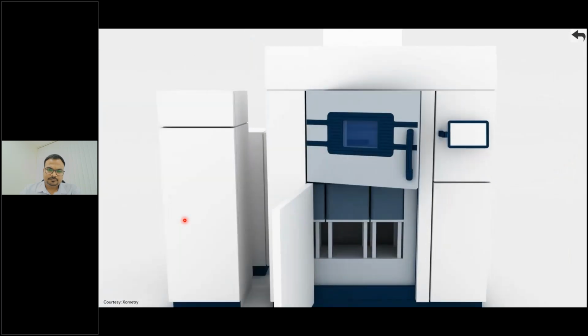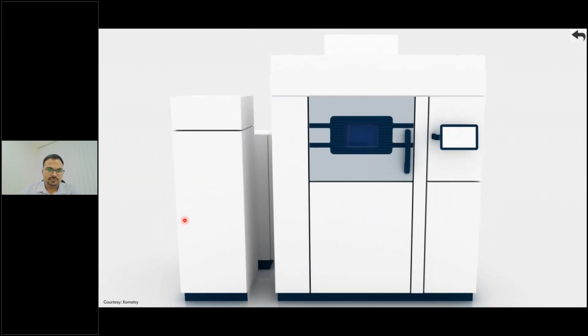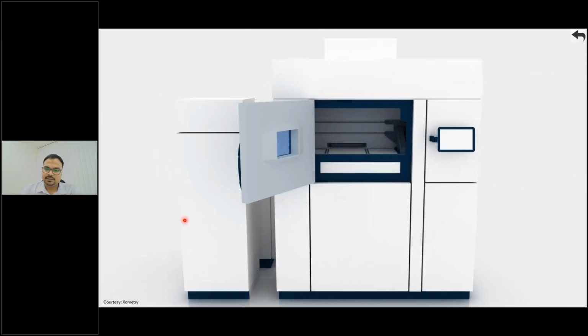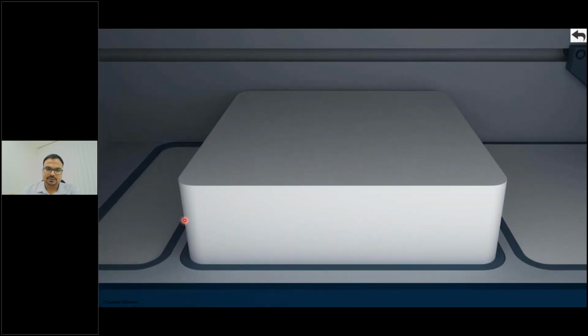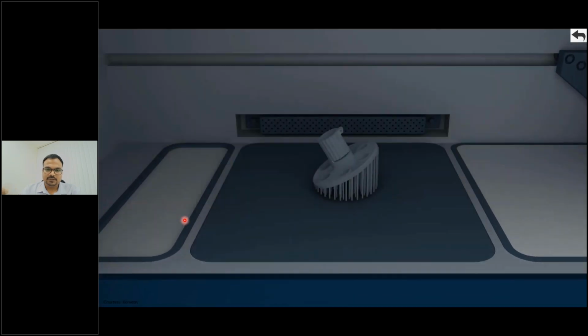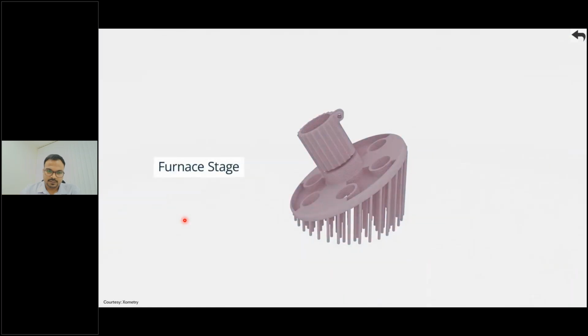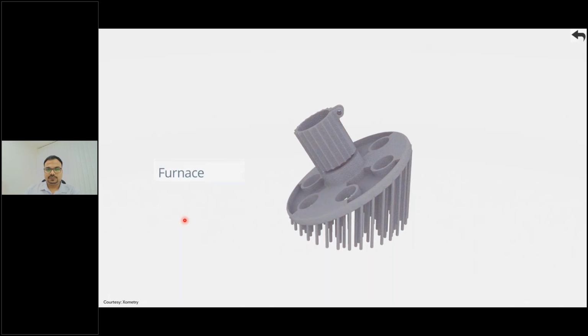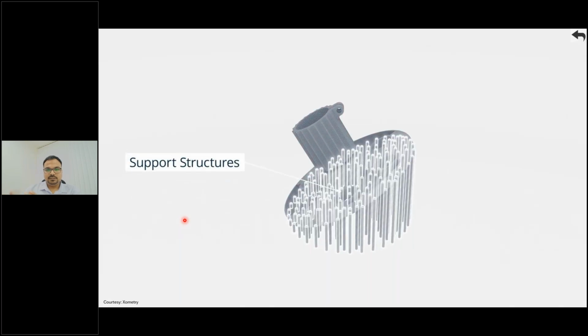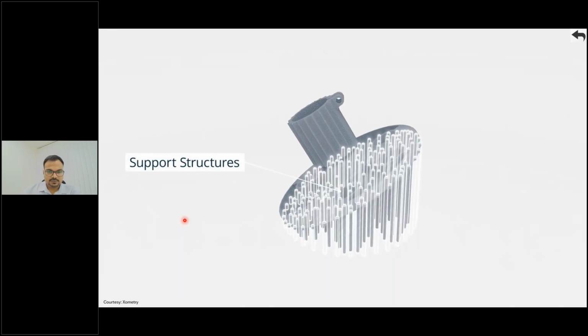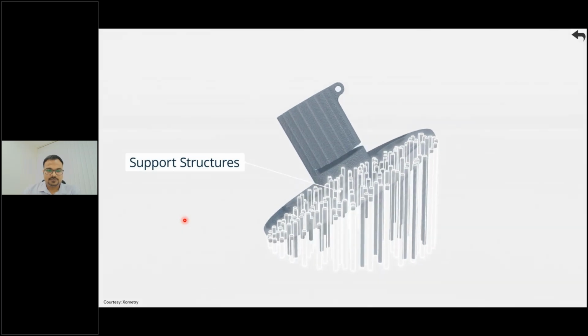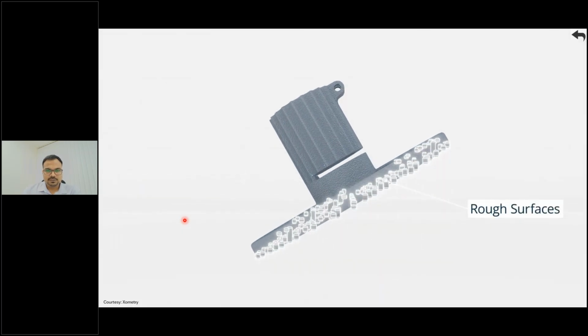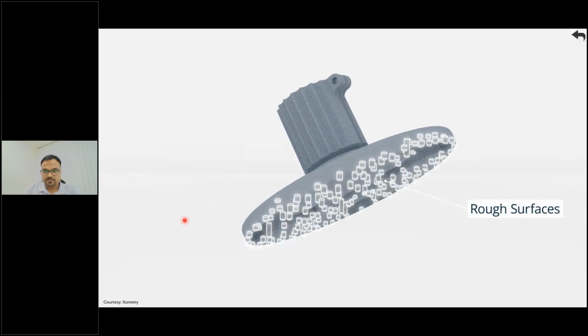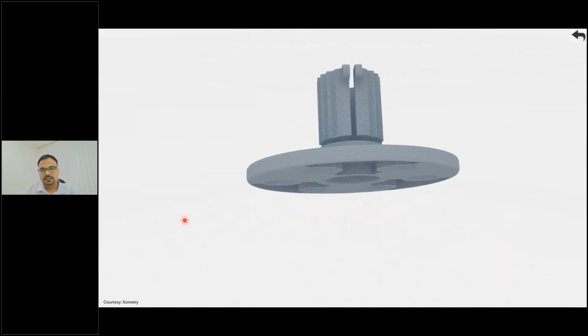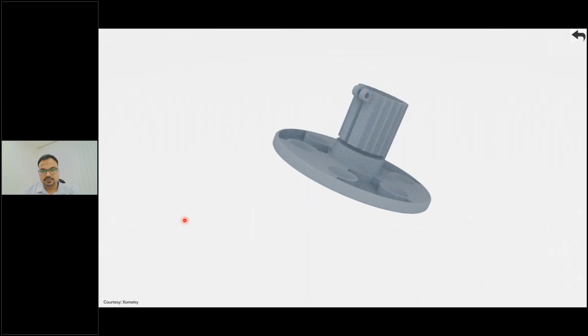And it addresses very minute details. The laser diameter is just 18 microns, so it is able to print starting from 100 micron of the feature as well during the process. Immediately after the printing is done, we take out the model and put it in the furnace for relieving the stresses, the residual stresses or the thermal stresses that are induced in the part, remove the support structure, and do the desired post-processing to control the tolerances and get your functional component.